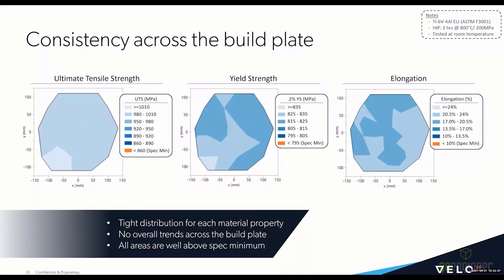When you look at these, really a couple of key things. First, all of the values are well above the spec minimum, in this case ASTM F3001. Additionally, you can see there's really no clear trends of variation across the build plate. And we're also getting a nice tight distribution across the plots. So very high values, tight distribution, and you're not seeing any trends.